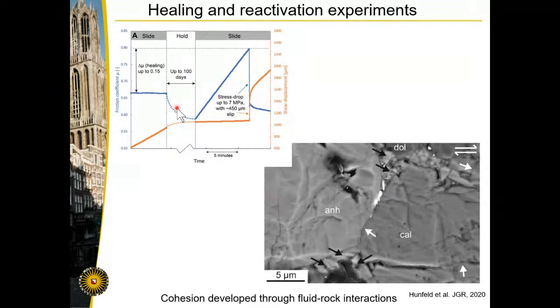Now, what is actually happening in these samples? We think that in especially the Zechstein samples, we observe this indentation of grains, where grains are dissolving into another grain and material is precipitating outside of this contact. We think that this causes some cohesion to be developed during the period of inactivity, and upon resliding, this cohesion has to be destroyed again, and that causes this stress drop after reactivation of our fault.